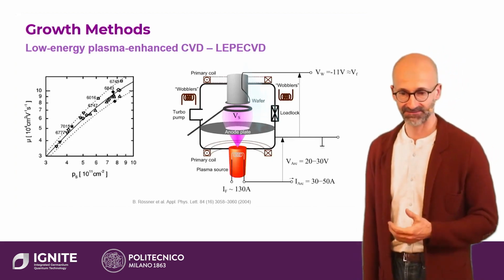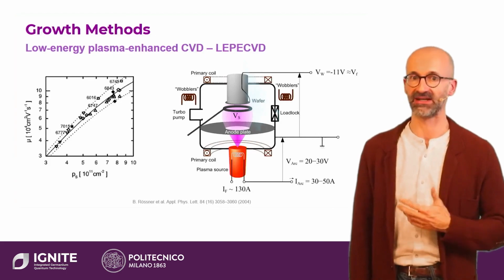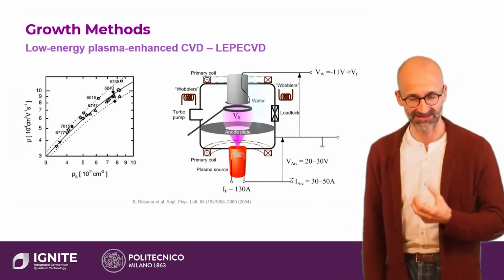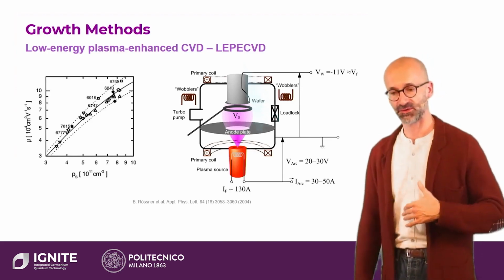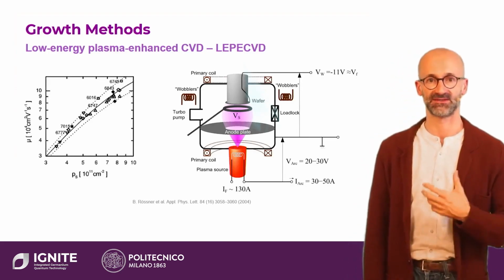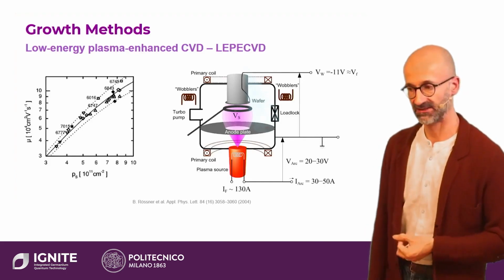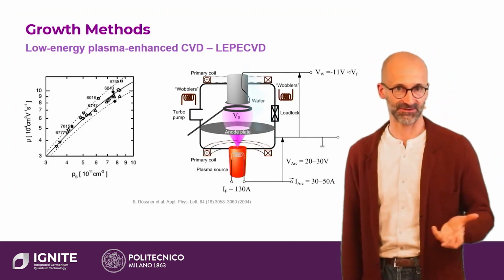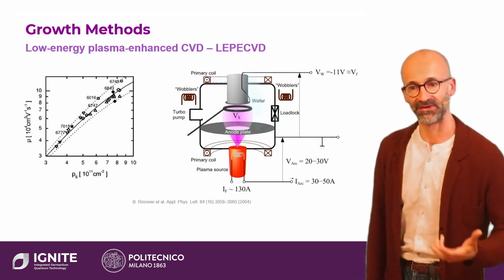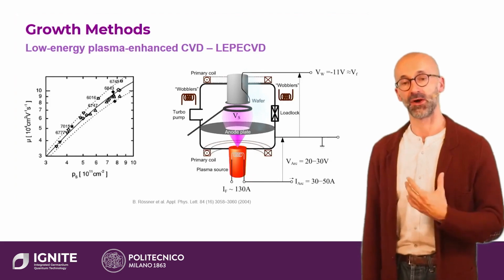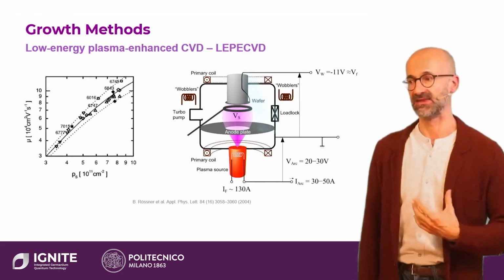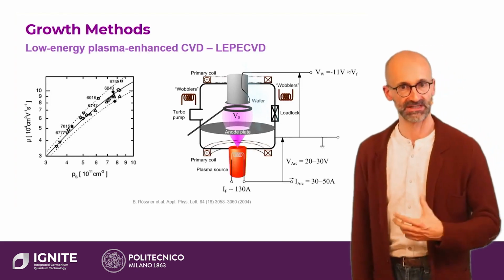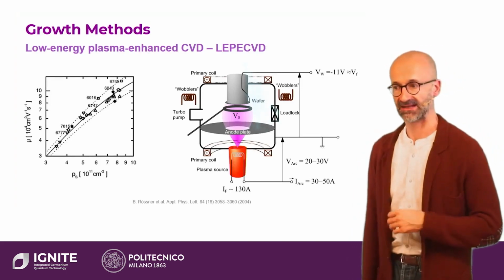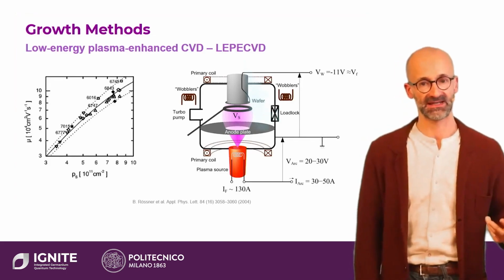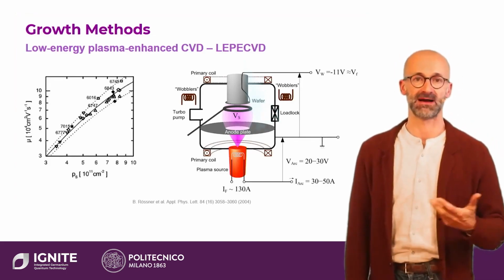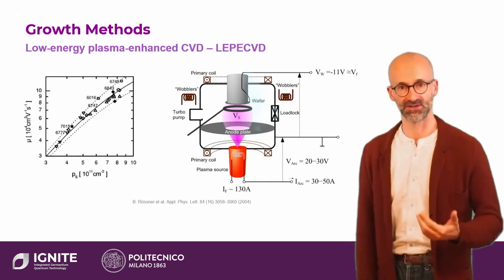Of course, this means that the growth is not necessarily of high quality. In fact, it's now up to the operator to balance the growth rate and the temperature, because if we grow too fast at too high a rate, the material may not even be crystalline. However, with great power comes great responsibility, but this extra flexibility means that we can grow very thick layers, we can optimize the temperature to get the best quality possible, and then by reducing the plasma density and reducing the gas flows, we can also grow these quantum wells at high precision, quickly enough to avoid relaxation and quickly enough to avoid contamination by background impurities, but also slowly enough to have good control of the composition.